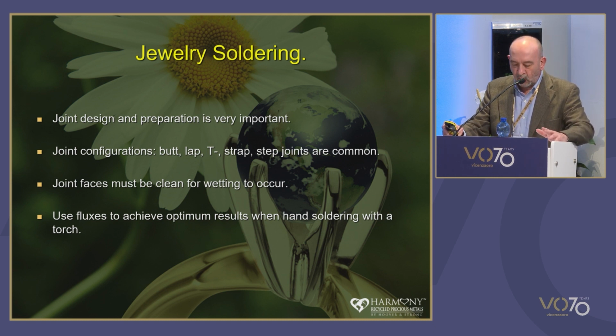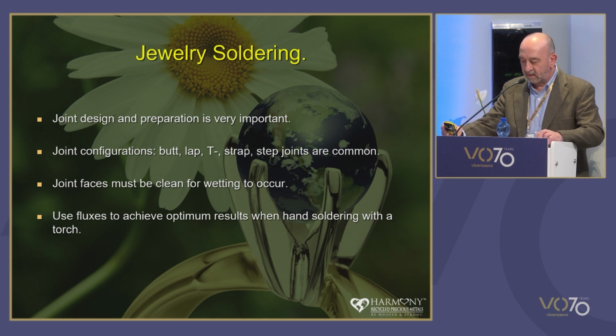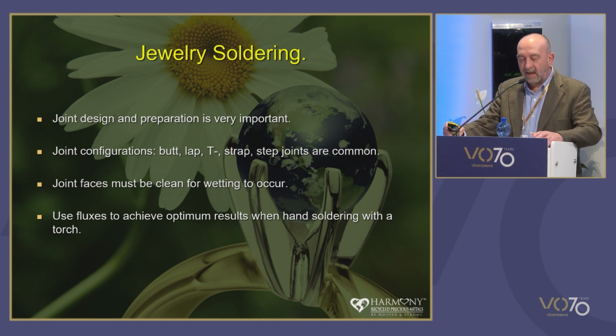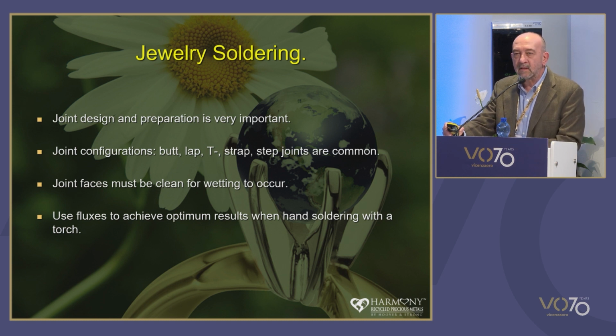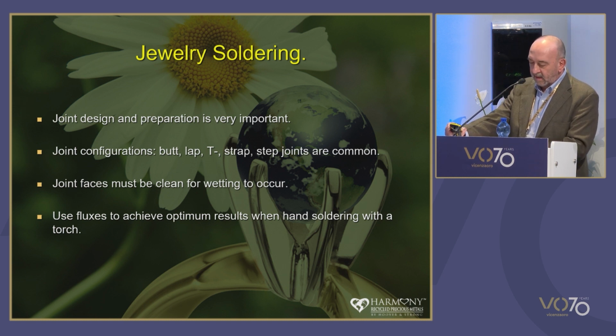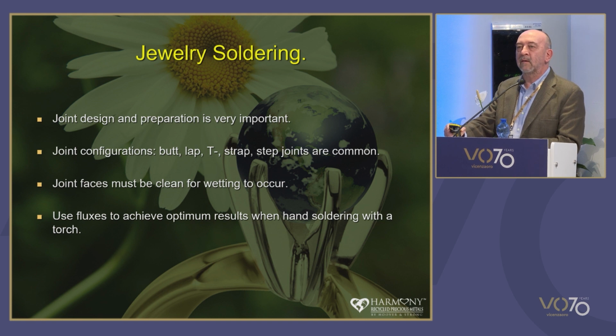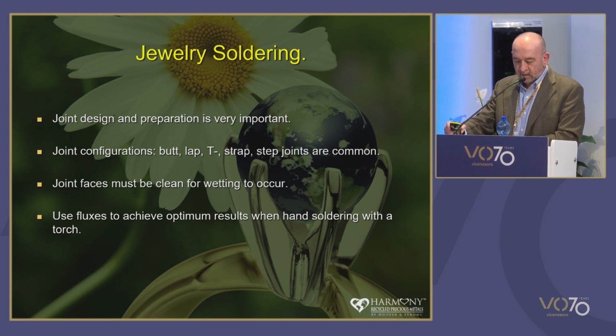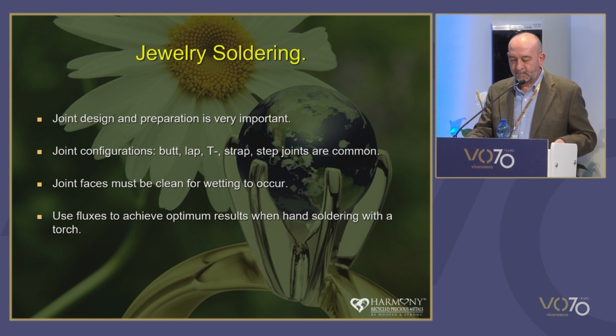Joint faces always need to be clean for wetting to occur. So filing and sanding is recommended to clean away dirt and grease. And the surface roughness is also beneficial because it can help by reducing the contact angle of the liquid solder, so it enhances the capillary action.